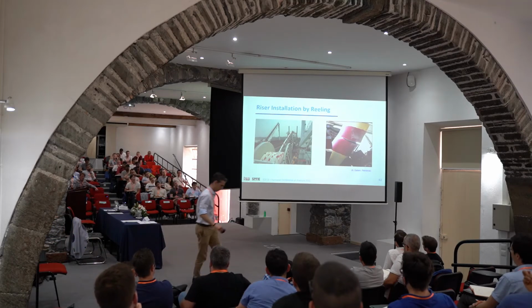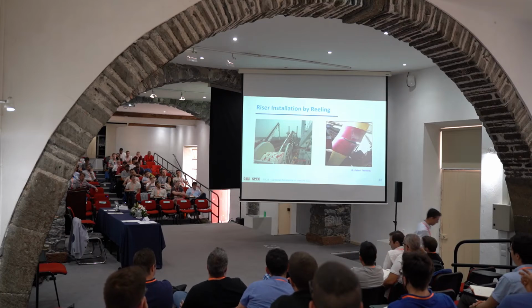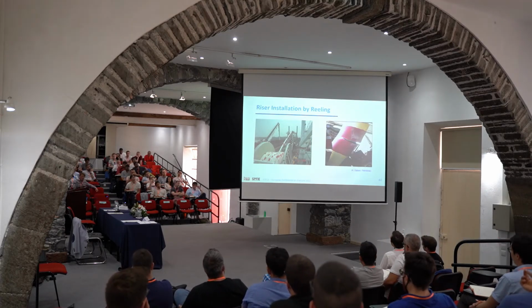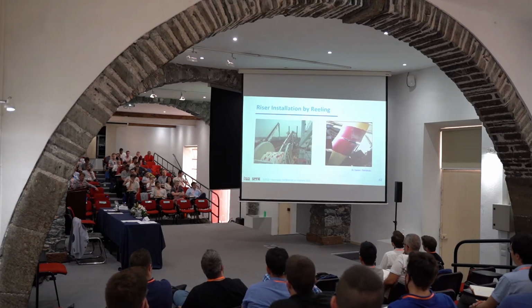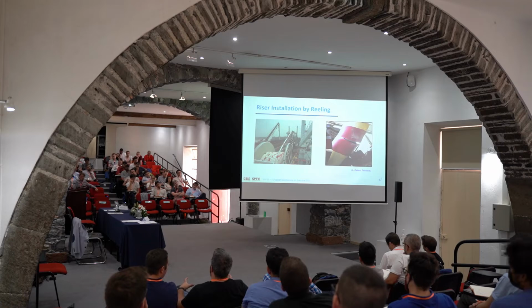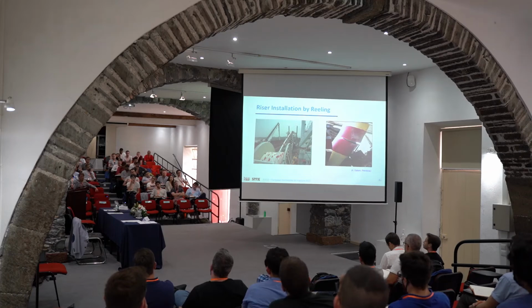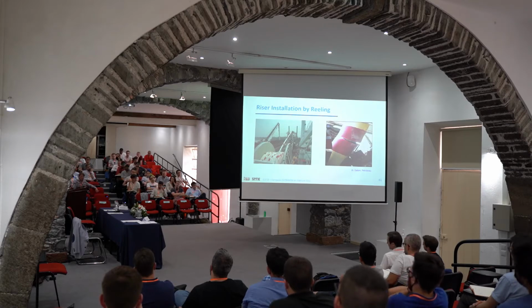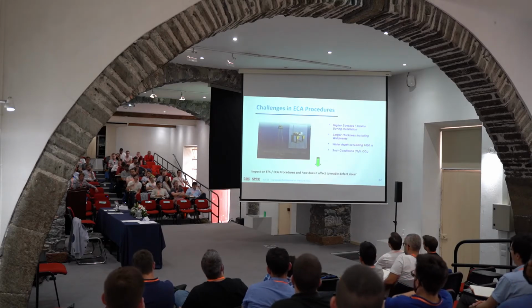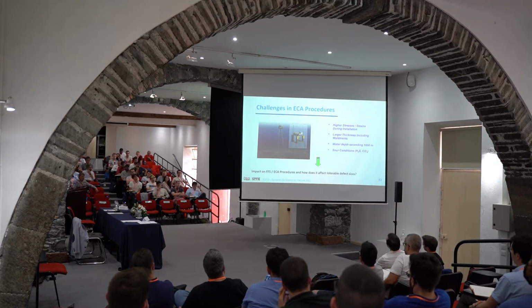So what do we have to do with this? This imposes a very challenging assessment during the installation. Actually, you can see here, the girth weld just broke apart because of the high strains, high stresses, and the plasticity. The deformation here is in the order of 3% beyond yield. That's a lot of strain. And those are the challenges that we have: high stresses, larger thickness, water depth exceeding 1,000 meters, and also sour service. This is also a nightmare.